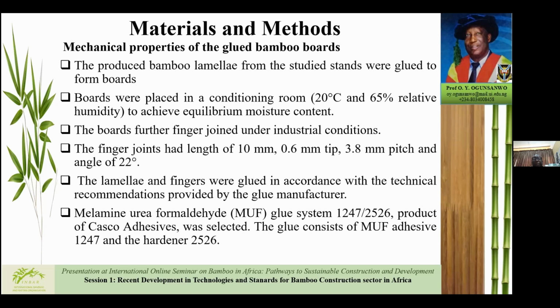Mechanical properties of glulam were tested. The produced bamboo lamellae from the study stands were glued to form boards, as explained earlier. Boards were placed in a conditioning room at 20 degrees Celsius and relative humidity of 65% to achieve equilibrium moisture content at that level. The boards were therefore finger jointed under industrial condition. The finger joints had a length, this is the specification of the finger joints, of 10 mm, 0.6 mm tip, and 3.8 mm pitch at an angle of 22 degrees.